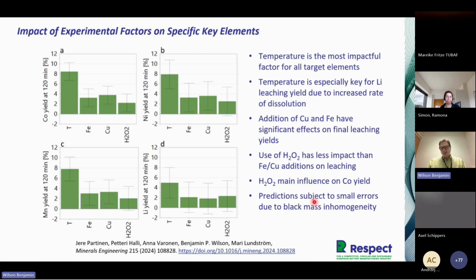But it was clear from our results that temperature is the most impactful factor for all the elements, thinking about cobalt, nickel, manganese and lithium in this case. And temperature was found to be especially key for lithium. These graphics here show the impact of each individual parameter on the yields based on the statistical analysis. But it's clear also that the addition of copper and iron have a significant effect on the final leaching. Interestingly enough, peroxide has less of an impact when compared to the addition of iron and copper, but peroxide was found to be quite important for the leaching of cobalt, so the cobalt yields.